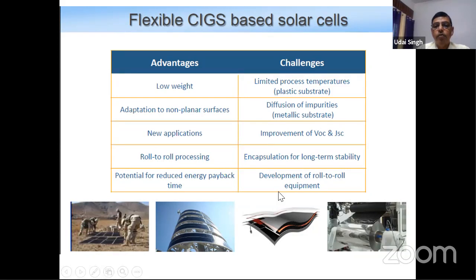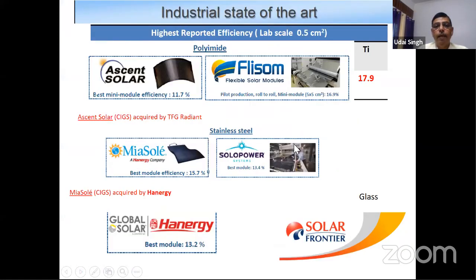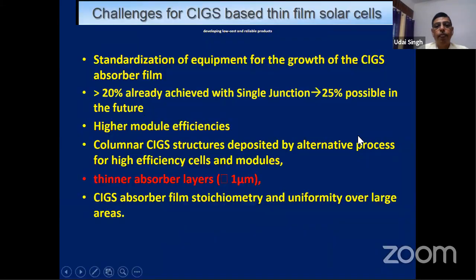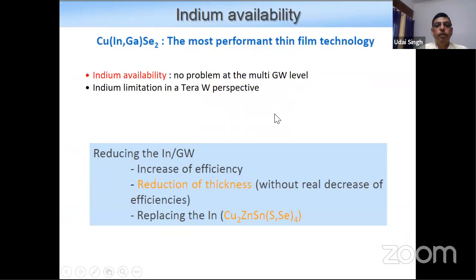There are certain challenges also: limited substrate temperature, because plastic substrates cannot go above 400; diffusion of impurities from metallic substrates; improvement of open circuit voltage and short circuit current; and then the encapsulation. So these are certain challenges that still exist in this material. If you see now, these many companies are still left working on this. The challenges I have already discussed, so I will skip this.